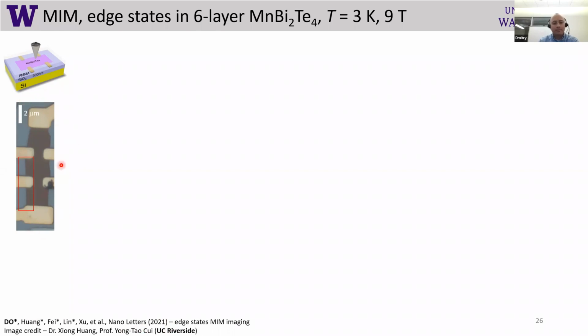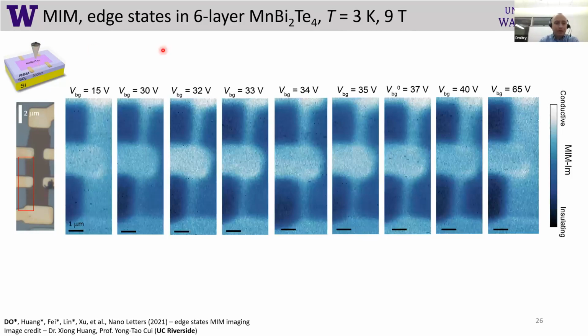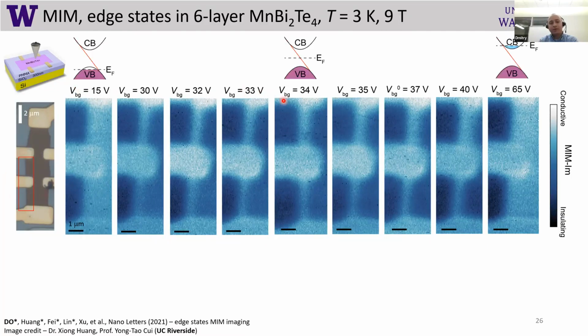So here we have a small Hall bar device, and I'll be showing you this region here outlined in red, and the measurements are done with a sharp tip, essentially with a resolution of roughly 100 nanometers. So these maps are maps of conductivity in this particular region as a function of backgate voltage. As a reminder, backgate voltage essentially just changes the position of your Fermi level. And in this case, we have a 9 Tesla field applied. So our samples are in a topological state.